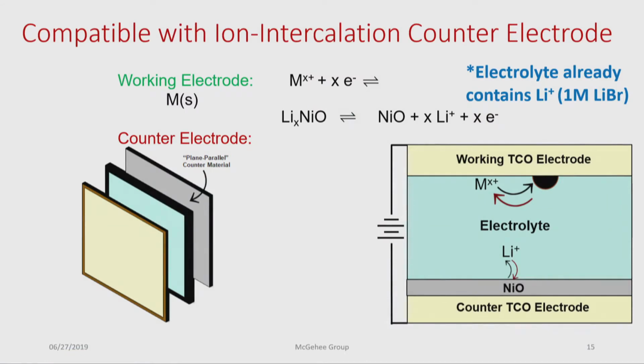So we had a wide range of potential materials that we could have worked with. And after many trials, we eventually stumbled on, surprisingly, one of the most commonly pursued electrochromic counter-electrode materials, which is nickel oxide. And nickel oxide was an attractive candidate for us because it's anodically coloring, meaning that it colors at opposite potentials at which our metal deposition takes place. So we can actually have both electrodes color at the same time. So we can establish a dual coloring dynamic electrochromic technology.